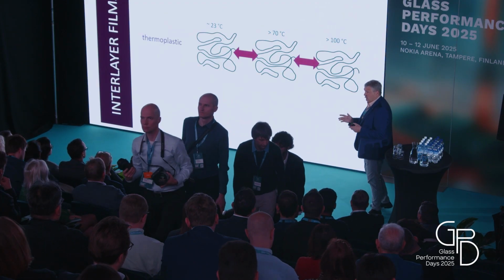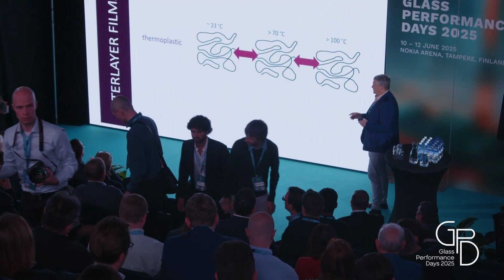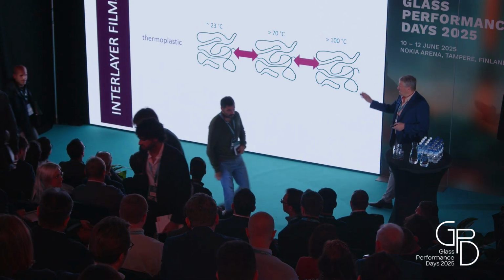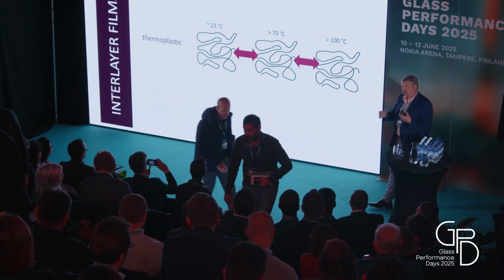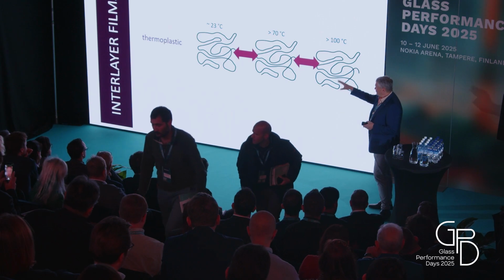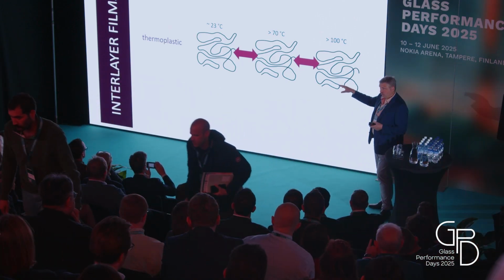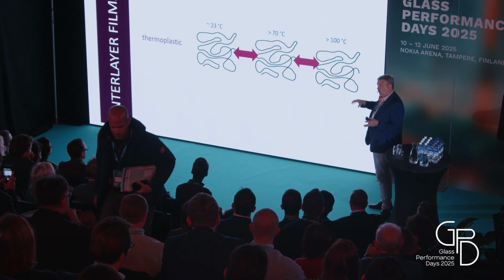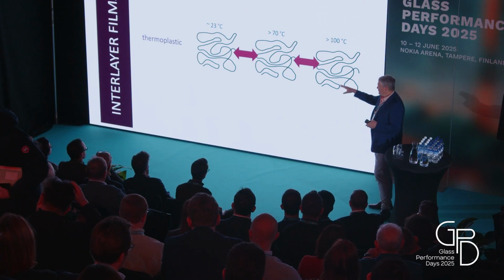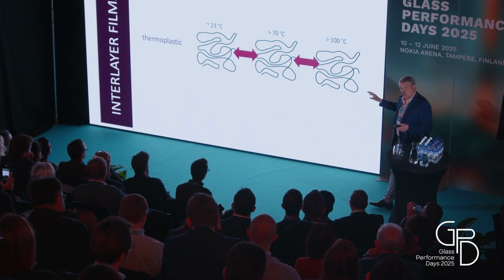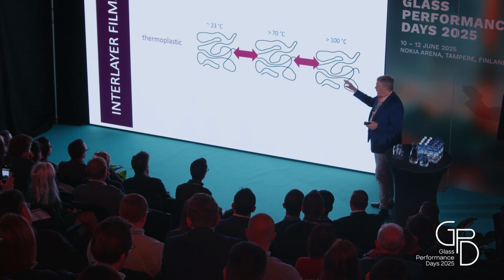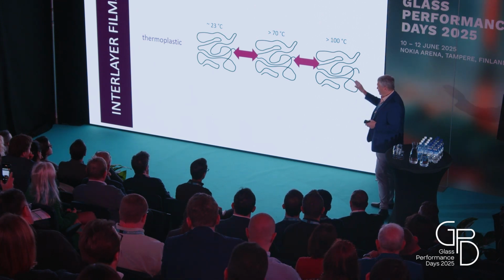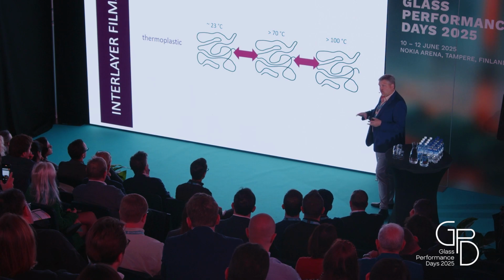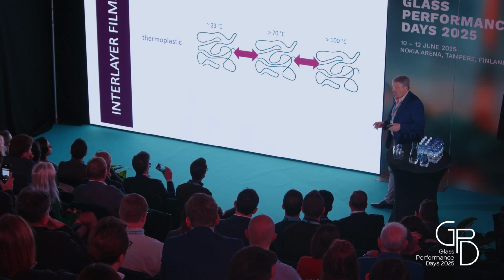depending on the requirements. The cross-linking, what does this mean, or the difference between thermoplastic and duroplastic-elastomeric films? What you can see here is an entangled polymer chain, right? At different temperatures. So you see a thermoplastic polymer behaves at different temperature, more or less the same. It can widen a little bit, but the structure of the polymer chain remains more or less the same all the time, independent what temperature you have. You can always go from one to another material. It's in this temperature range we are talking about. It's all the time the same. Compared to this,